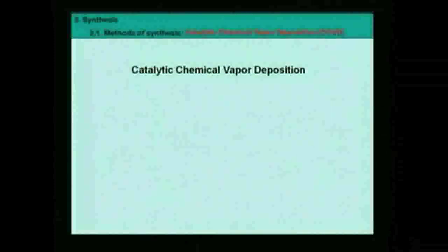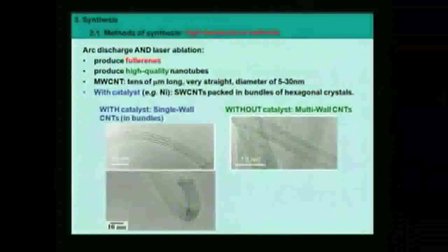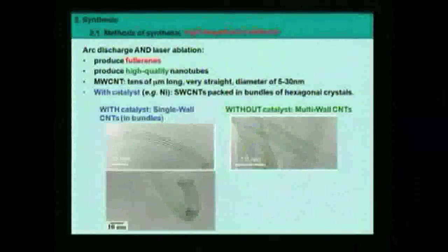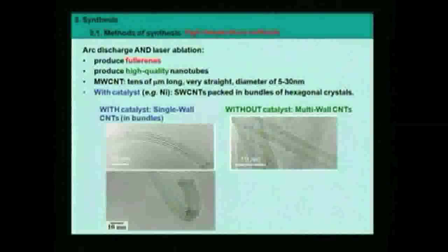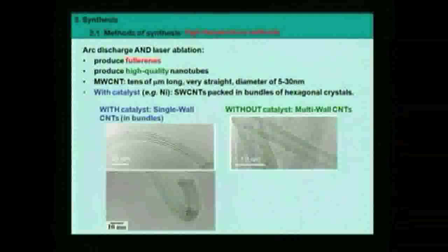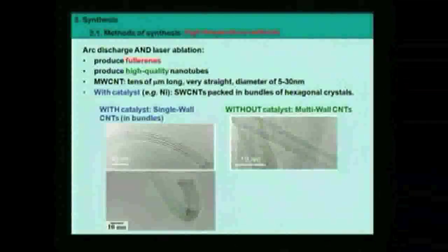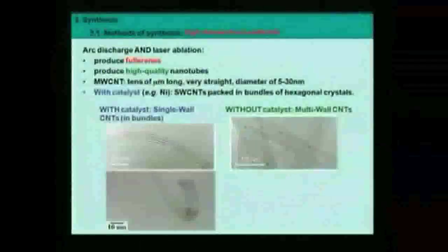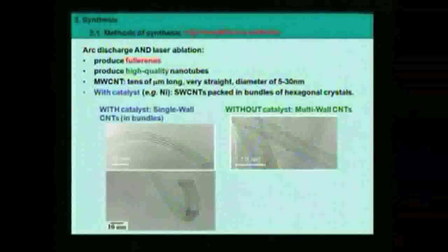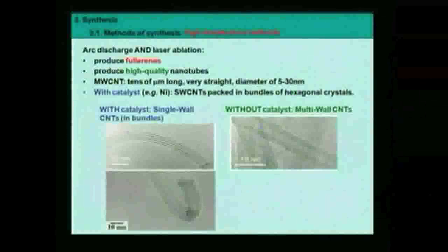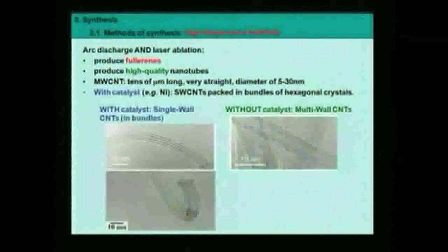The first question is about the effect of the nature of the catalyst on the obtained product. So actually there are many effects in terms of yield. The catalysts giving the best yields are usually nickel, cobalt and iron. In addition, it was discovered about 10 years ago in Montpellier that if you add some amount of other elements like yttrium or lanthanum, you will increase the yield by several orders. This is not well understood yet, even now. Experimentally, I can say that the best elements are usually nickel, cobalt mixed with an addition of another lanthanide element. And also, when you change the nature of the catalyst, you will change the diameter of the nanotubes.